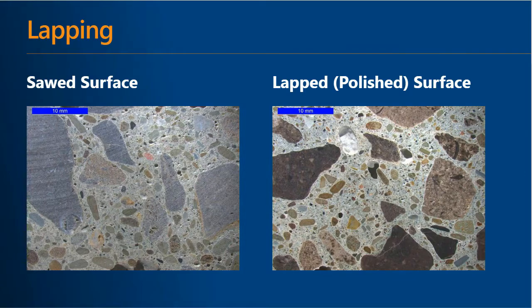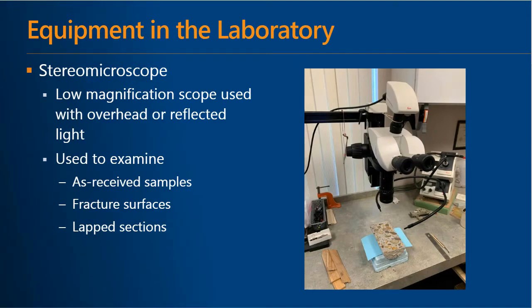start to pop. So the edges of aggregate particles are crisper, we can look at the air void system, and we can look at some of the larger features, typically using a stereo microscope. And so a stereo microscope is a relatively low magnification microscope that we can put any type of sample underneath. We use an overhead or an external light source to reflect light off of our sample that goes up through